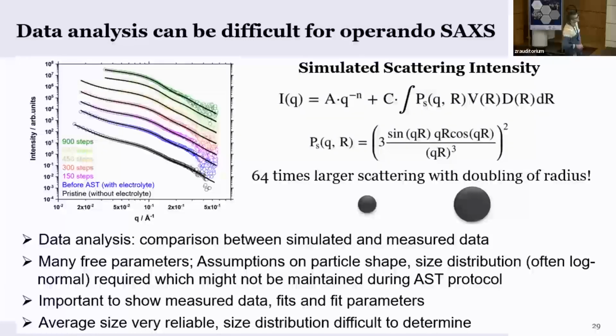But for example, adding smaller particles doesn't change your signal so much. So the amount of small particles is not easy to extract. And so basically in the measurement, you always assume the same size distribution, a log normal. But if you have degradation processes, that might change actually. So it's not given that you always have a log normal distribution. So that's a difficulty in the analysis. So average size is very reliable, but the size distribution for the Ostwald processes that are important, it's very difficult to extract.